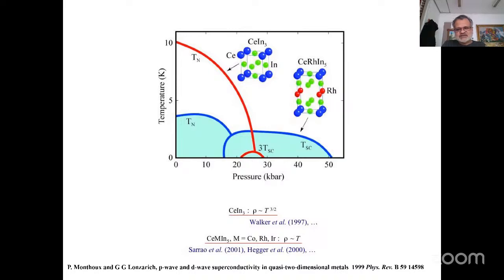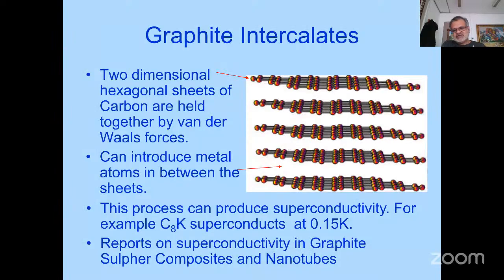So this sets up to consider how we can potentially make these kinds of systems more directly accessible. In my case, I initially started with trying to intercalate graphite, HOPG, with magnetic species to see if we can make a two-dimensional superconductor. The idea being that you have a magnetic material which is 2D now by making it that way rather than growing it that way. And then you have the hexagonal structure, which arranges the spins in the system and gives us two handles, i.e. the next nearest neighbor frustration will give quantum fluctuations in the system, conceptually speaking. Or if we have a material like, in our case, ytterbium, if we compress it, it changes the valence state and will induce magnetism. So that was our attempt.